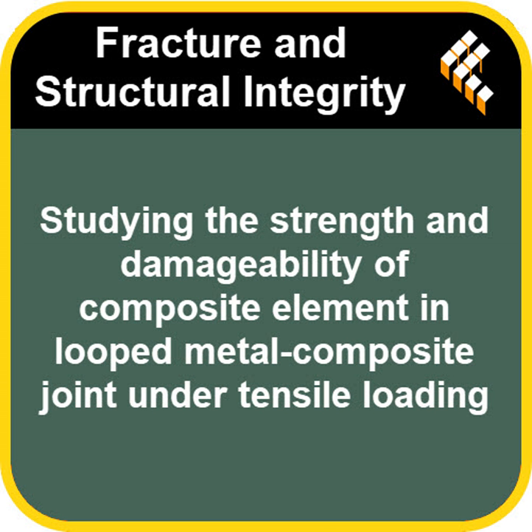Directly. They measured the loop's thickness in that maximum loading zone. Remember, it started at about 6.4 millimeters. After 200 kilonewtons, it went down to 6.15 millimeters. And after the full 300 kilonewtons, it was down to 5.8 millimeters. That's quite a squeeze. It is. They calculated it as a 1.1 times compaction.